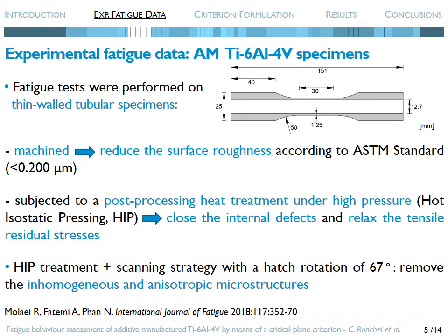All fatigue tests were performed on thin-walled tubular specimens with the geometrical sizes reported in the present figure. After manufacturing, AM specimens were machined in order to reduce the surface roughness according to the ASTM standard. Then, such specimens were subjected to a post-processing heat treatment under high pressure, named hot isostatic pressing, HIP, which allows closing the internal defects and relaxing the tensile residual stresses. Such a treatment, together with the scanning strategy consisting in a hatch rotation of 67 degrees, are able to almost completely remove the inhomogeneous and anisotropic microstructures of the present material.